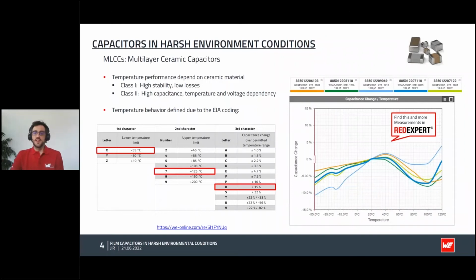Let's start with the common ceramic capacitors. The electrical and thermal performance is defined by the used ceramic material. We use two main classes of materials. The MLCCs with class 1 materials have a very stable characteristic in the whole temperature range and have extremely low loss. Class 2 materials, on the other hand, have a much larger dielectric constant, so we get higher capacitance values, but they suffer from voltage and temperature dependencies as well as aging.